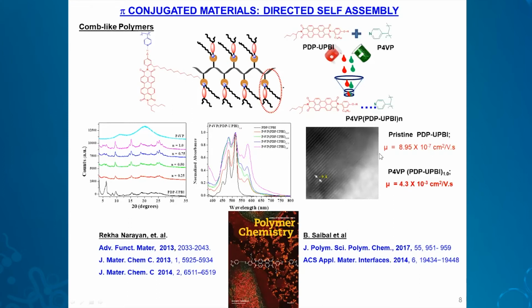And the most important proof came from the charge transport measurement. We measured the electron transportability of the pristine perylene molecule, which was in the 10 power minus 7 range. And after self-assembling them, when we check the mobility of the self-assembled supramolecular comb polymer, it has increased by 4 orders to 10 power minus 3, which is a proof that our hypothesis has been valid. So we have extended this approach to various types of perylene and naphthalene molecules and designed in several ways.